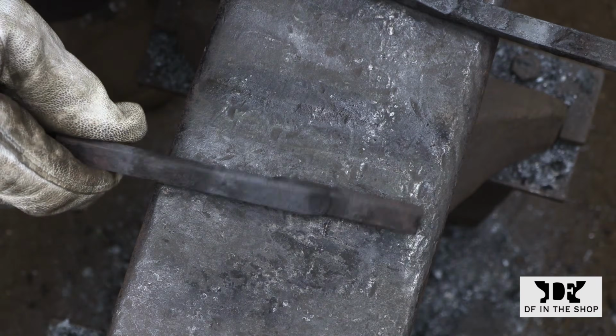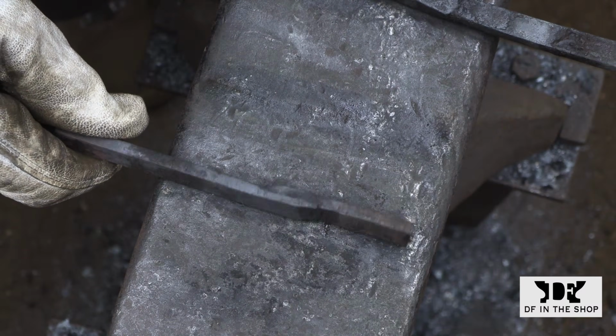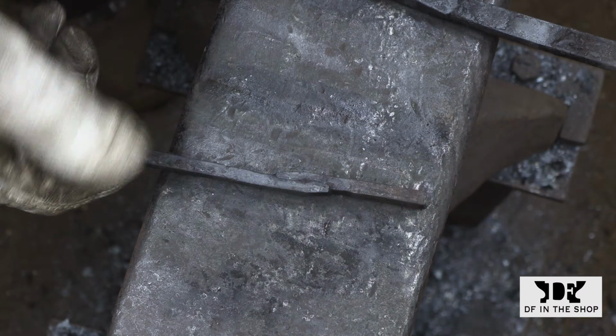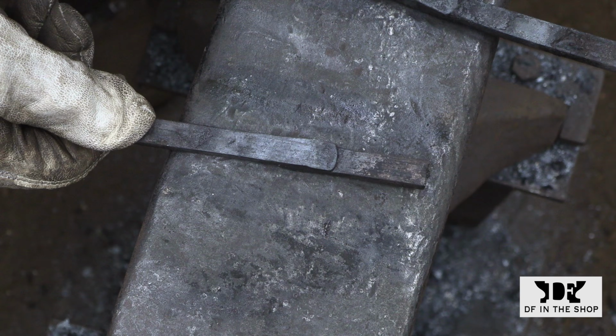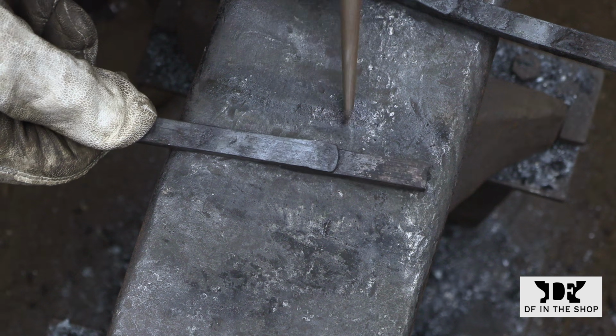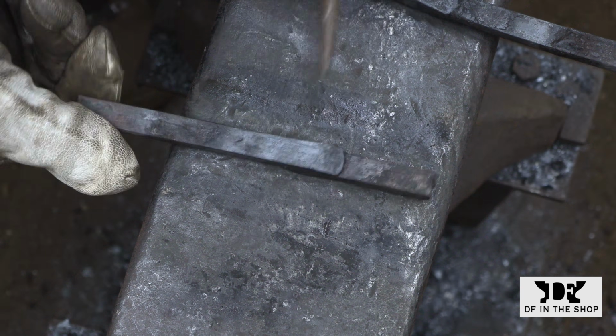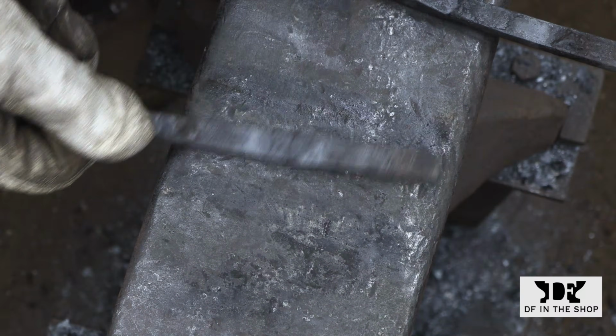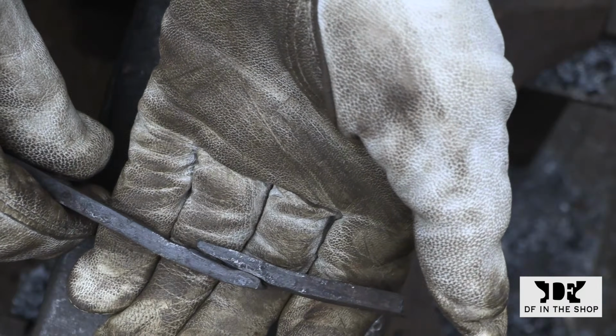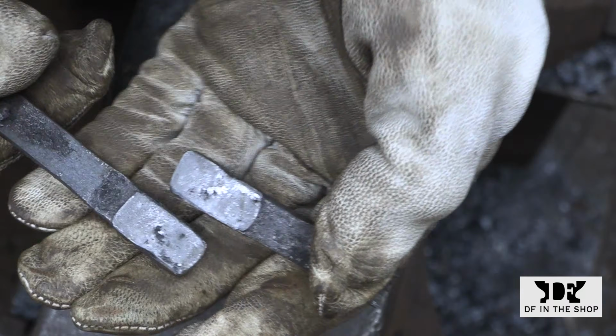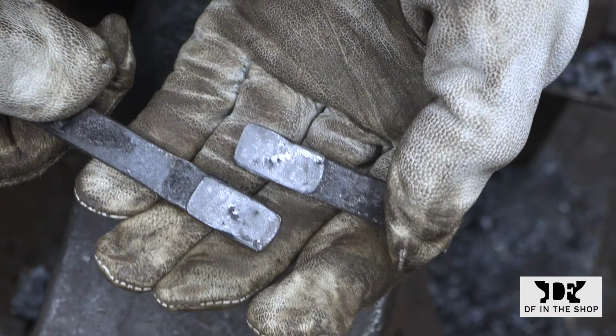So here's a sample for this weld, and you can see how the ends of the weld, the scarf joints, are still a hard line. They should be blending into the rest of the bar, but even at this stage there is evidence that there are problems with this weld. And the bend test shows that it took absolutely no effort to break this weld.